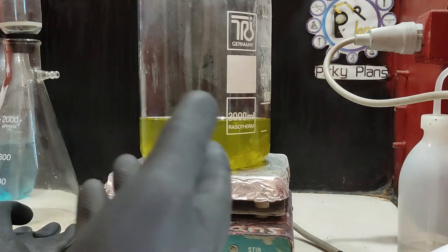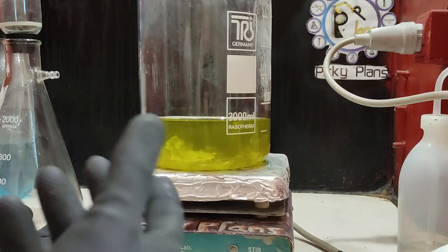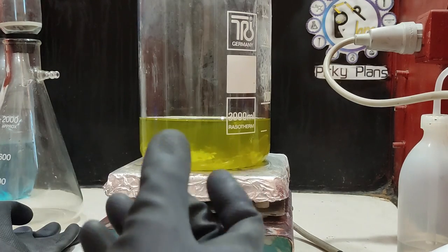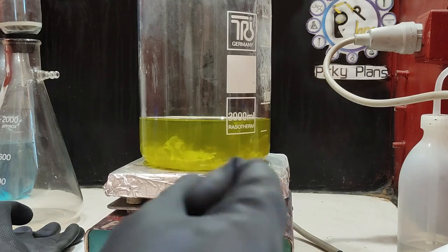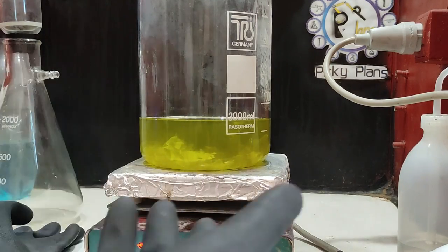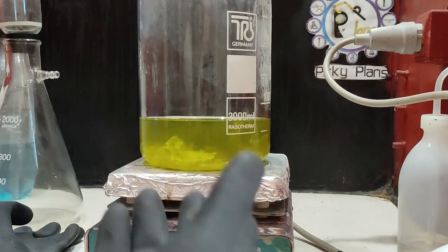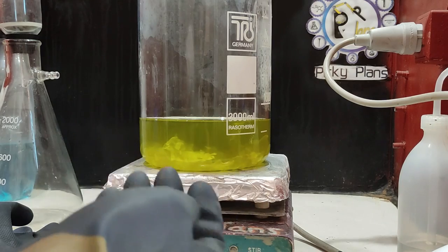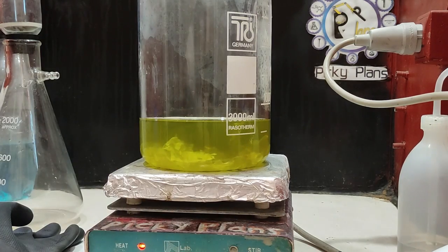as she said, you can add some crystals of nitrate like potassium nitrate to the solution to help with precipitating and sticking all suspended nanoparticles of whatever it is. Usually it's metal sulfate or oxide. But in my experience, using some pieces of filter paper would be helpful, just enough to get rid of this turbidity.